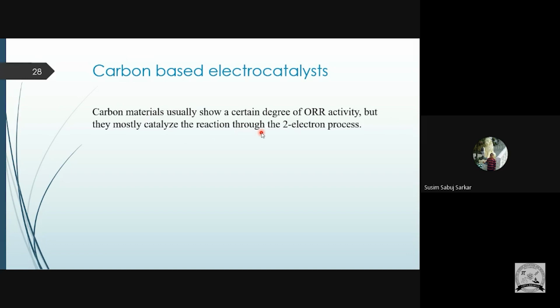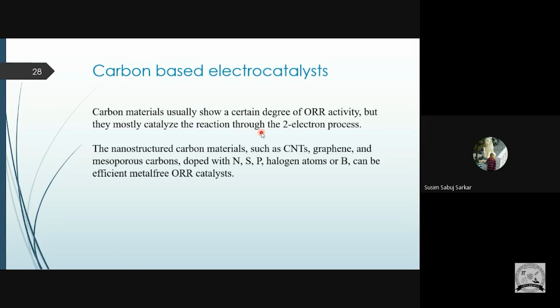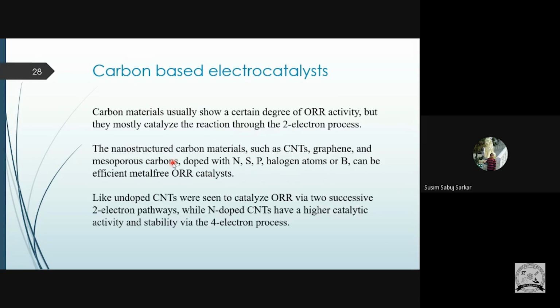So we can improve the carbon material, that means carbon nanosheets, by doping. The carbon nanotube, graphene, or mesoporous carbon can be doped with nitrogen, sulfur, phosphorus, any other halogen atom, or boron, and can be efficient ORR catalysts, and this will be a metal free catalyst. We are not using metal. Also, undoped CNT can catalyze ORR via two successive two-electron pathways, while when we dope the CNT with N, we get the 4 electron process.